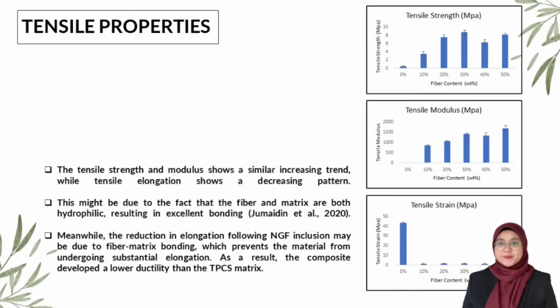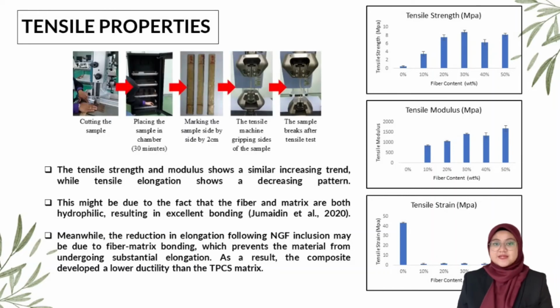For the tensile properties, the tensile strength and modulus show a similar increasing trend, while tensile elongation shows a decreasing pattern. This might be due to the fact that the fiber and matrix are both hydrophilic, resulting in excellent bonding. Meanwhile, the reduction in elongation following Napier grass fiber inclusion may be due to fiber-matrix bonding, which prevents the material from undergoing substantial elongation. As a result, the composite developed a lower ductility than the TPCS matrix.